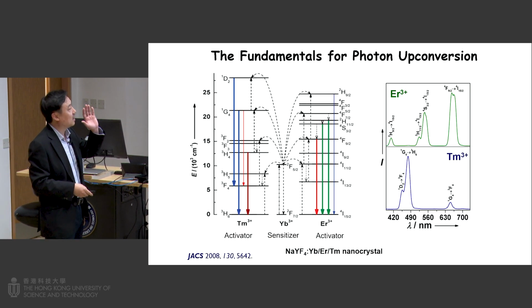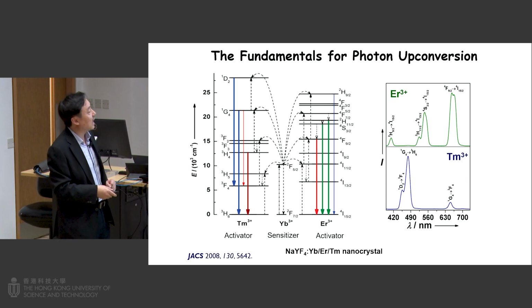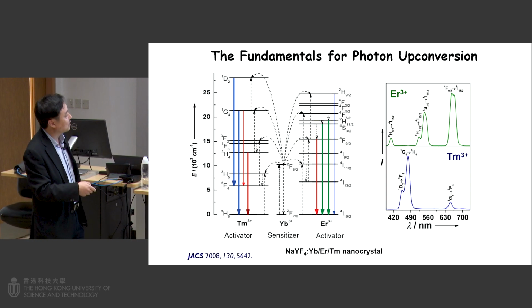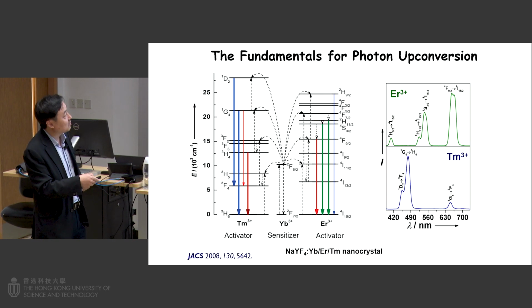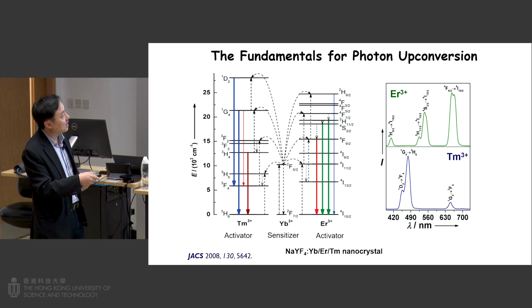So this is the fundamental principle of upconversion. I just want to quickly go through that. Typically we use sodium yttrium fluoride, doped with Yb as a sensitizer, and Tm and Er as the activator. Sometimes we call them emitters. All these energy transitions correspond to these emission bands. You see the 4 emission peaks correspond to Er, so you have 4 different energy transitions, and you can match all these transition bands with the emission bands. For Tm, you also have 3 emission peaks coming from these energy bands.